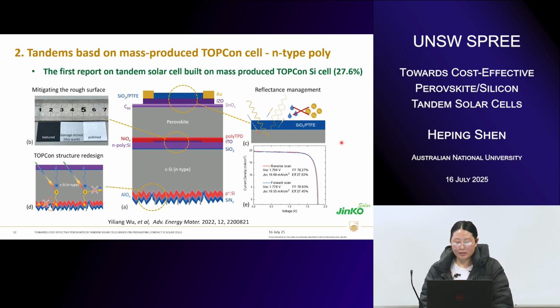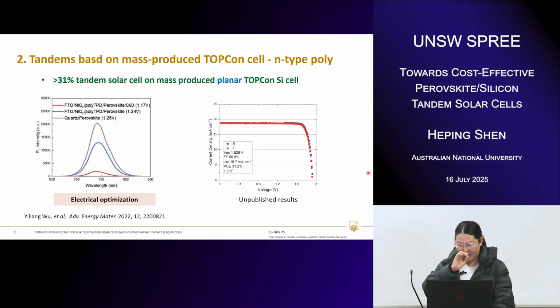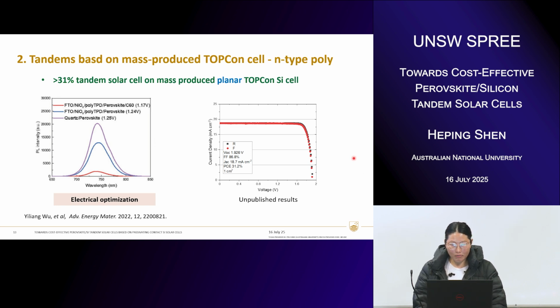Another important innovation in this work is that we replaced the conventionally used anti-reflection layer based on magnesium fluoride with this silicon oxide PTFE composite, to allow better prevention of the penetration of moisture and oxygen, because these layers show much better coverage and much fewer cracks in the film itself. Okay, so that's our first report on the tandem on TOPCon.